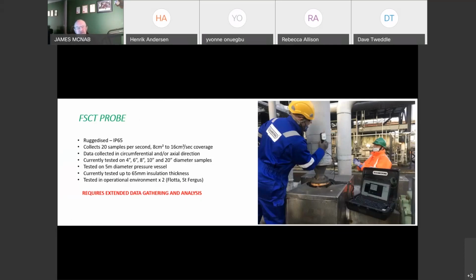It's currently been tested in 4, 6, 8, 10 and 20-inch diameter pipe samples, mainly on corrosion that was found previously and had some reparations. So we're looking for samples that have actual corrosion that have not been repaired to test it on.